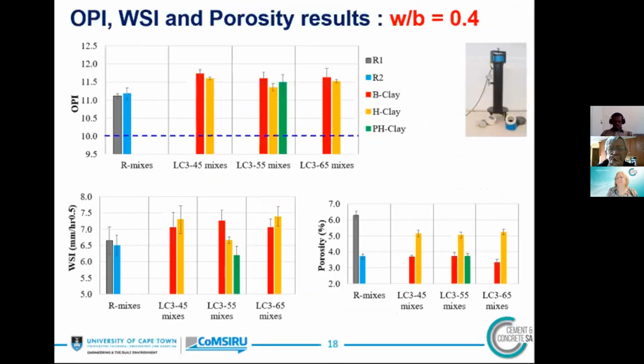Now here we have durability index test results. This is the case of 0.4 water binder ratio. You can see all mixes have OPI values greater than 10, and sorptivity and porosity less than 10. So here one can conclude that all these mixes are very dense and have high resistance to penetration of deleterious gases such as carbon dioxide. But just looking at the OPI values, it's clear that the LC3 mixes are better than the reference mixes. In the case of sorptivity, all mixes are almost similar. Coming to porosity again, the LC3 mixes are better than the reference mix 1, but similar to reference mix 2, except this LC3 mix with H clay.